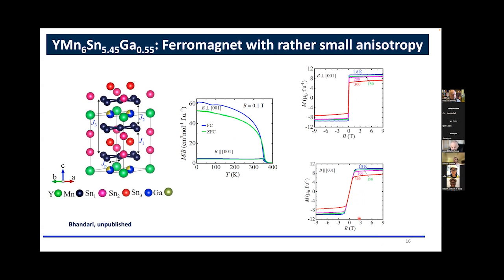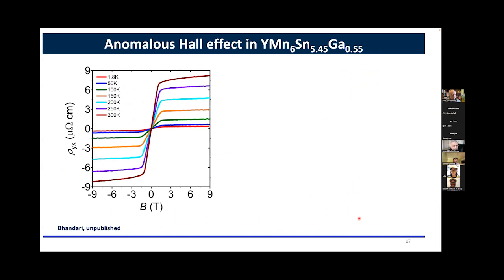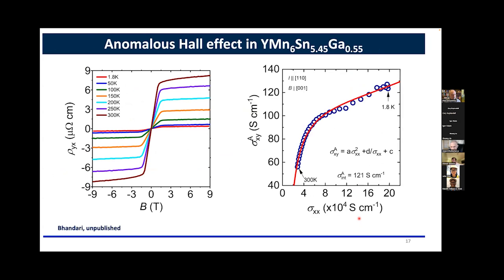Now, this provides us a nice way to test our hypothesis of whether that 1 over sigma XX term is coming from fluctuation or not, right? This one shouldn't have that much fluctuation because there is no terbium here. It's only manganese, maybe a little bit of fluctuation. Now, we measured the anomalous Hall. We can measure it down to 1.8 Kelvin pretty easily. And we did the scaling behavior on this one also. But the shape is pretty much the same.